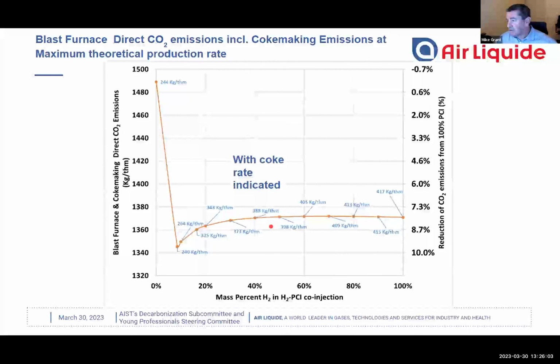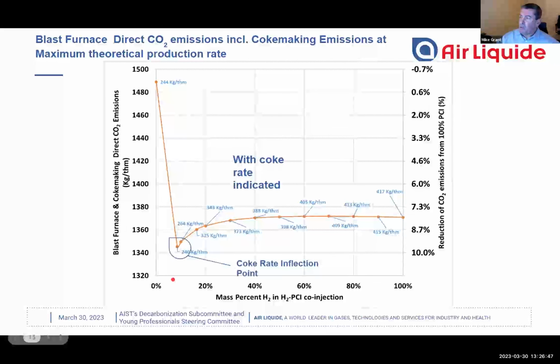Looking at this graph from a coke rate standpoint, you could see the reason we get success in the initial hydrogen injection is because we're able to maintain our coke rate. We're replacing PCI with hydrogen until we get to this point here. And this is very low coke rate. These are theoretical numbers, but it explains the effect. And then at this point, the coke rate needs to be increased again. And when we finally replace all of the PCI, we're back up to about 400 kilograms of coke. And this is why normal operators would stay in this region here, the coke rate inflection point.